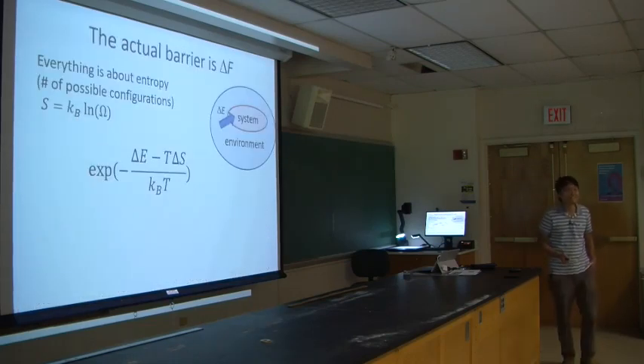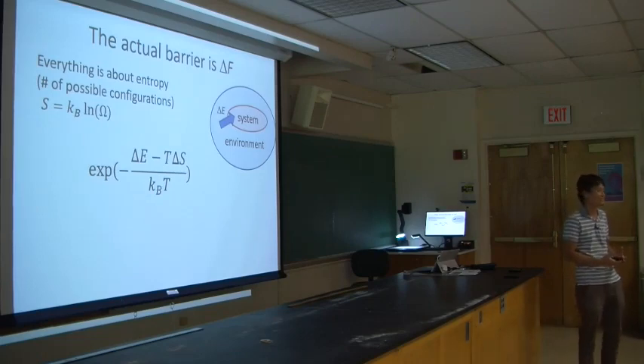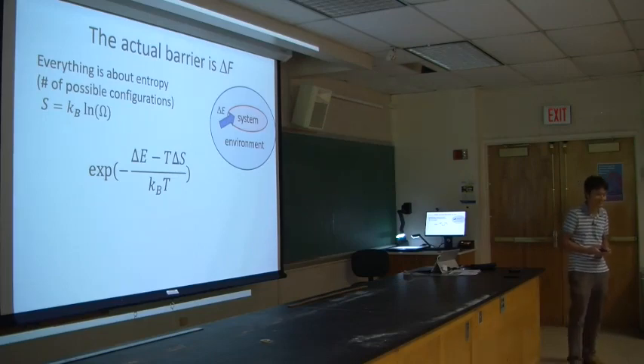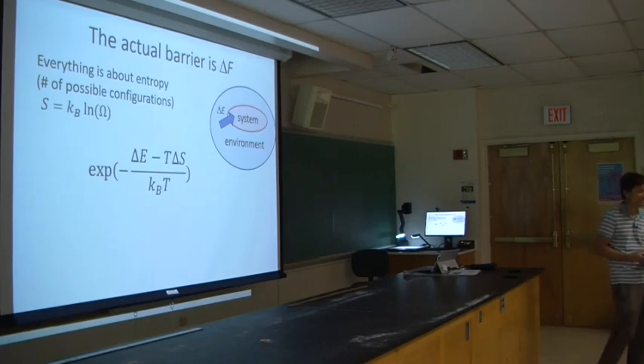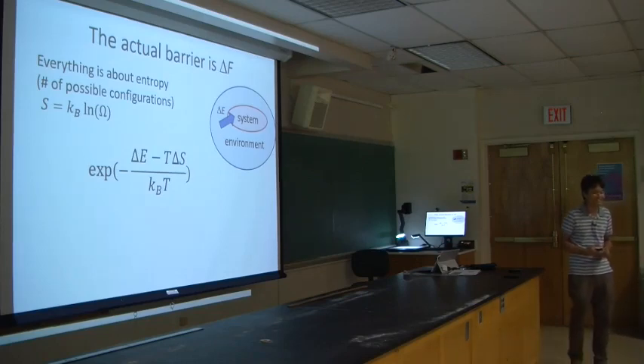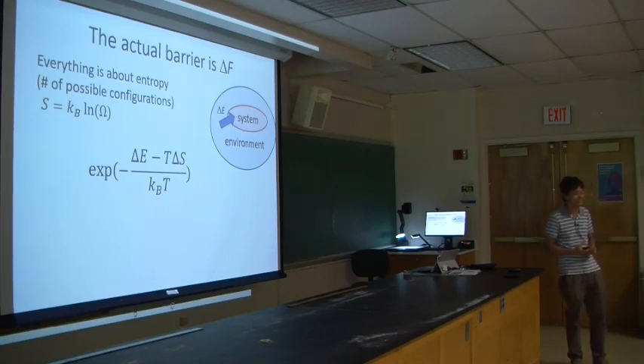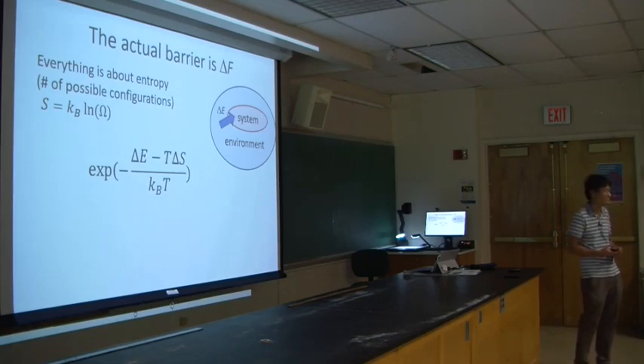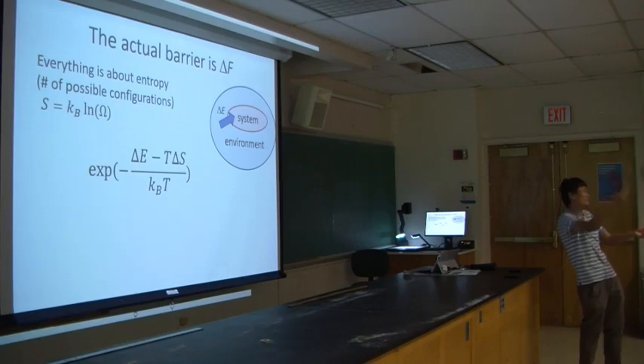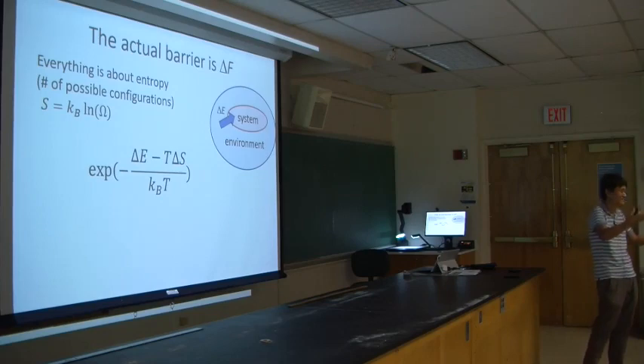So what happened is that we think that the actual barrier, we cannot use that delta E, right? If you go to basic thermodynamics, you know there's something called free energy, which accounts for the entropy. But usually, people working in this area sometimes overlook the effect, because they think about two molecules, so you can't have the entropy change too much, right? No matter if it's hot or cold, you still have just two molecules. You cannot really drastically increase the number of configurations, right?